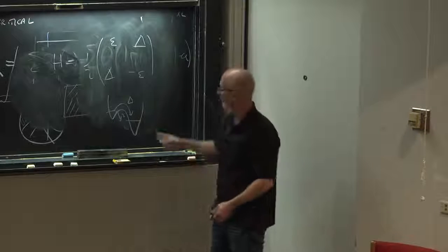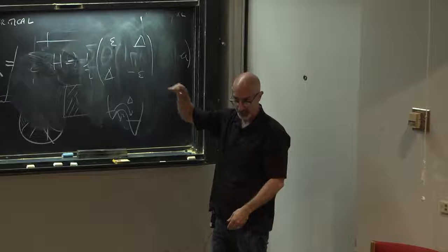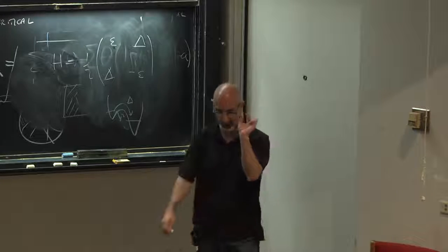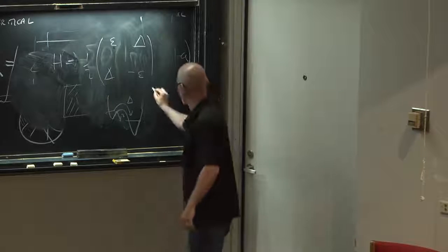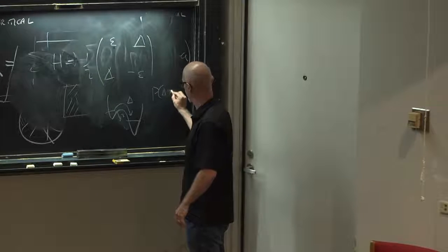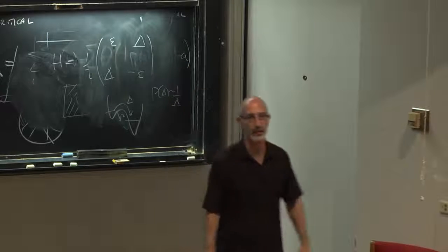And you're at very low temperature, you can basically take whatever distribution you want. And if it's even in that variable, you can take it to be flat around small energy. For the probability of the tunneling, they said the probability of the tunneling matrix element delta goes like 1 over delta. And this is easy to get from the WKB model of tunneling.